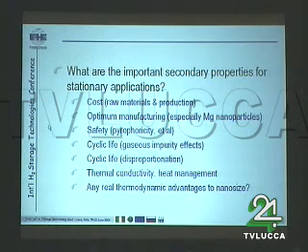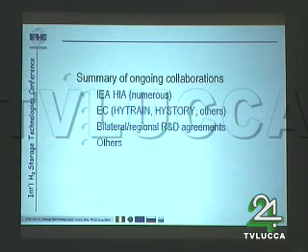What seems to be largely missed, in even the old-fashioned hydrides, is safety, pyrophoricity, tank bulging, and cyclic life, which is largely unknown. As Seiji said this morning, that's not only a gas impurity problem, but disproportionation problems relative to the stability of the alloy or the intermetallic itself. Thermal conductivity and heat management is a major problem. Maybe it's not our problem because it's basically a mechanical engineering problem, but we cannot escape it. And again, there was some debate on whether there are really thermodynamic advantages, other than kinetic advantages, to nano-sized materials.